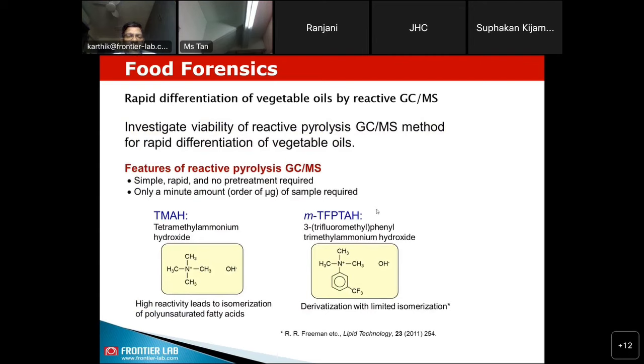But when you use pyrolysis GCMS, you can do it in situ. So you take the sample and the reagent together. Instead of methanol, we recommend TMAH for many of the reactive pyrolysis analyses. But for this particular application, we recommend trifluoromethylphenyl trimethyl ammonium hydroxide. The reason is when you do it with TMAH, it leads to more isomerization of these polyunsaturated fatty acids. Whereas if you use the TFPTAH, the isomerization is minimized. That means your data analysis becomes much easier compared to having more isomers. Okay, that's why for this particular analysis, we recommend using trifluoromethylphenyl trimethyl ammonium hydroxide.